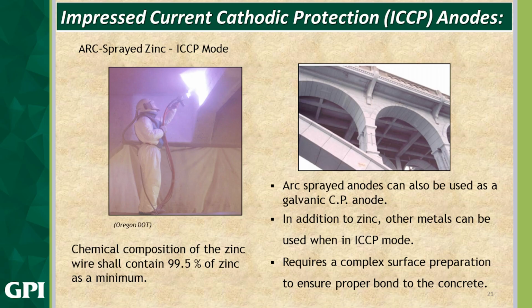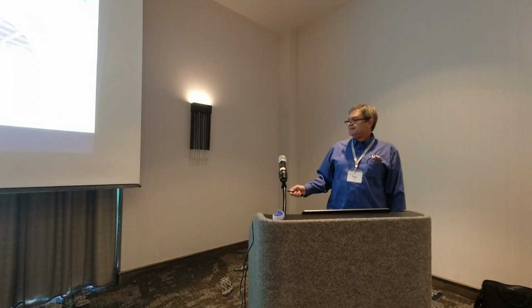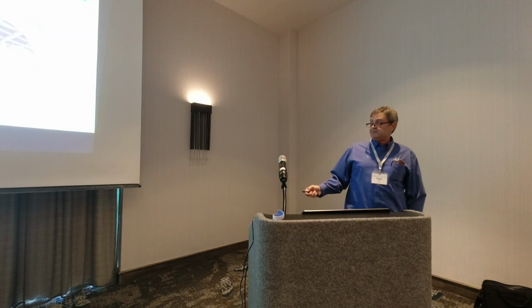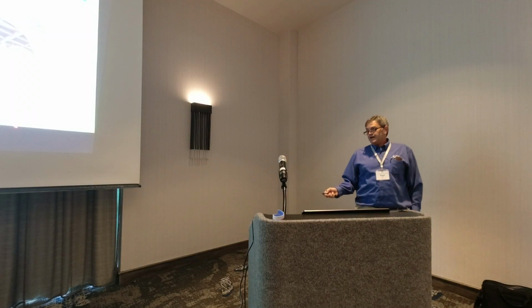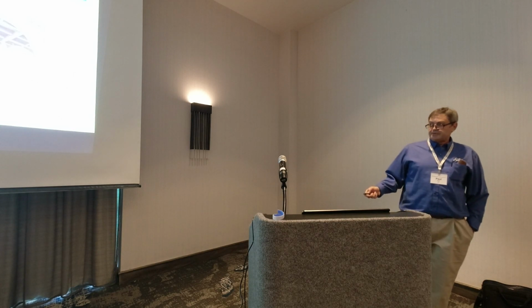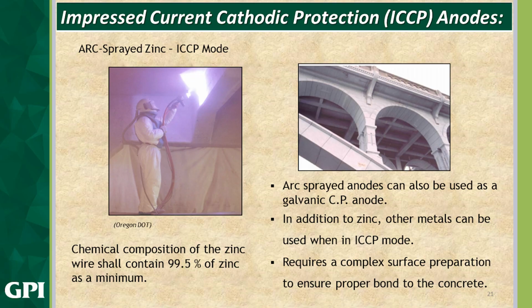Let's move now to impressed current cathodic protection anodes. Arc sprayed anodes can also be used in galvanic CP, but not only for ICCP. In addition to zinc, other metals can be used when in ICCP mode. It requires a complex surface preparation to ensure the proper bond with our concrete, and the chemical composition of zinc wire shall contain 99.5% zinc as a minimum.